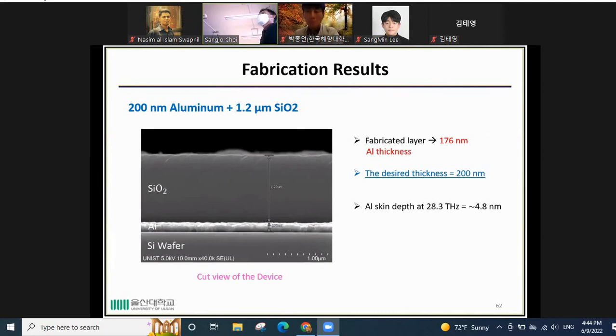And these are the fabrication results. This is the SEM image from the cut view. From the 1.2 micrometer silicon dioxide, and also 176 nanometer aluminum. So actually the desired thickness is 200, but in the fabrication we achieved 176. But I think this is acceptable because the aluminum skin depth at 28.3 terahertz is around 4.8 nanometer.